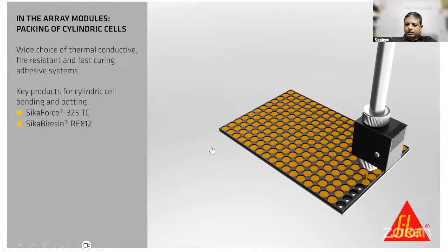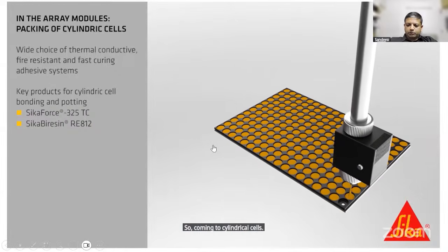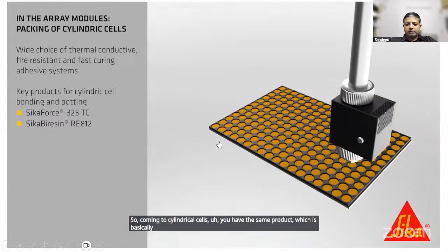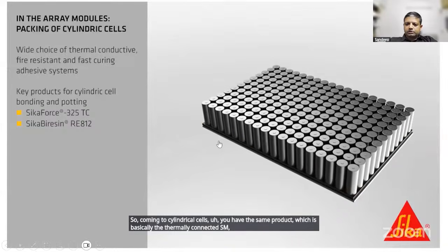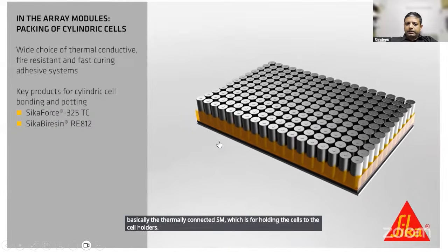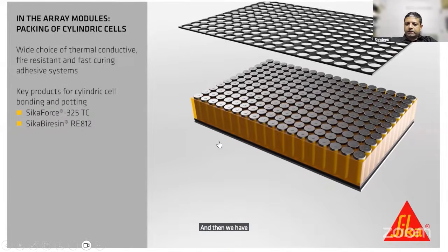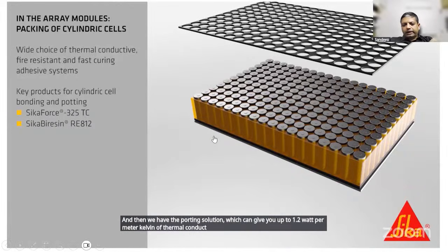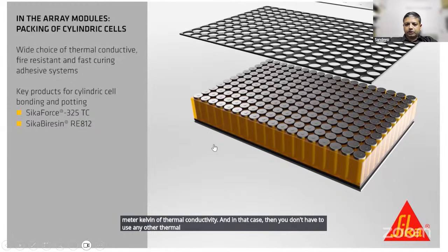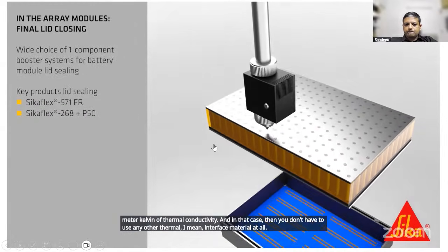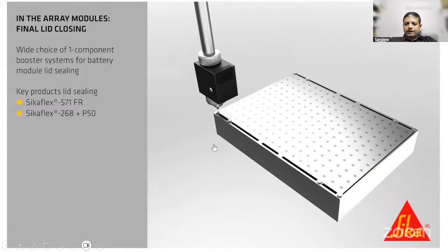Now coming to cylindrical cells, you have the same product, the thermally conductive adhesive, which is for holding the cells to the cell holders. And then we have the bonding solution, which can give you up to 1.2 watt per meter Kelvin of thermal conductivity. In that case, you don't have to use any other thermal interface material. And the lid is sealed again.